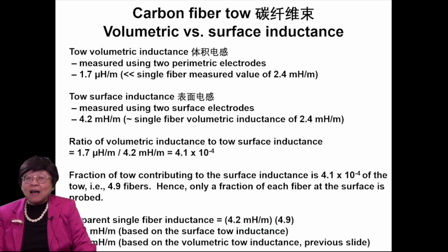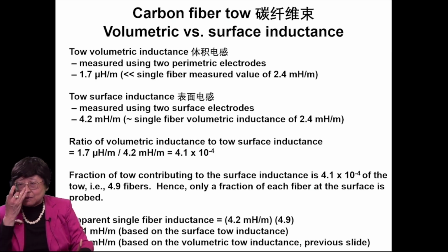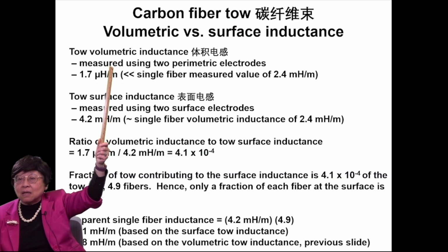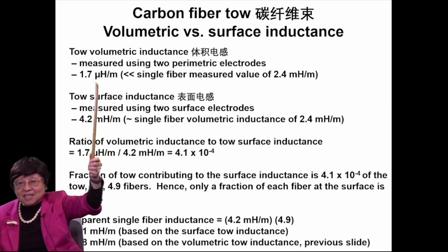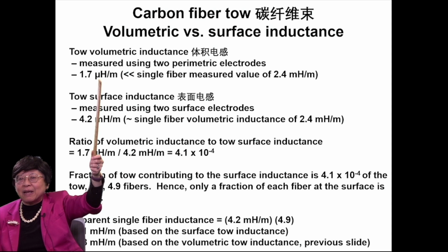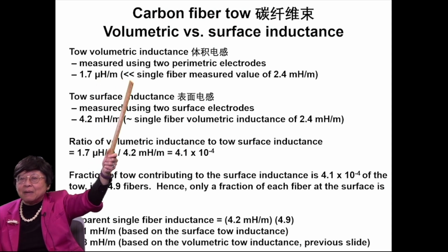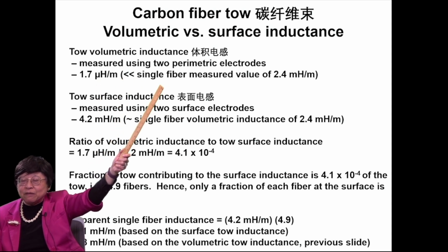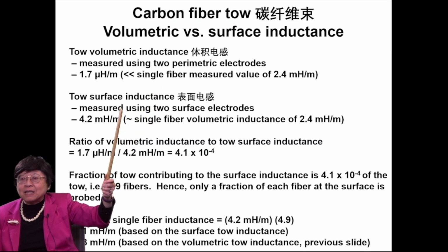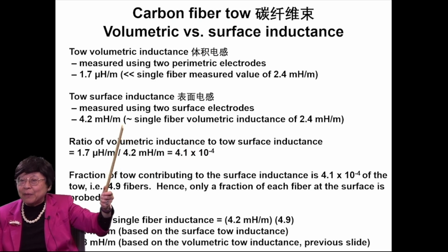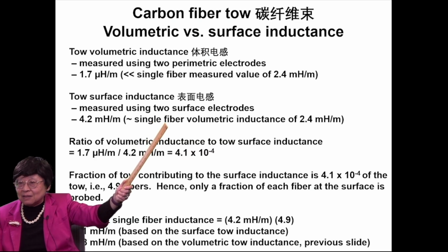Let's consider carbon fiber tow, comparing volumetric inductance versus surface inductance. The volumetric inductance of the tow, as I already said, is very little, 1.7 microhenry per meter, much less than the single fiber measured value of 2.4 millihenry per meter. But the tow surface inductance, measured using two surface electrodes, is 4.2 millihenry per meter, about equal to the single fiber volumetric inductance of 2.4 millihenry per meter.